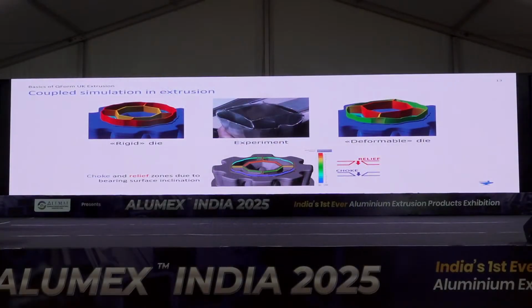If we consider some particular extrusion case where the tool deformation is not taken into account at all, the result will be completely different if you compare the experiment result and the result from the left side. While we use the default approach that Qform uses with a deformable die, where not only any deviation or displacement of the core during the extrusion, but also the formation of so-called relief choke angles are considered.